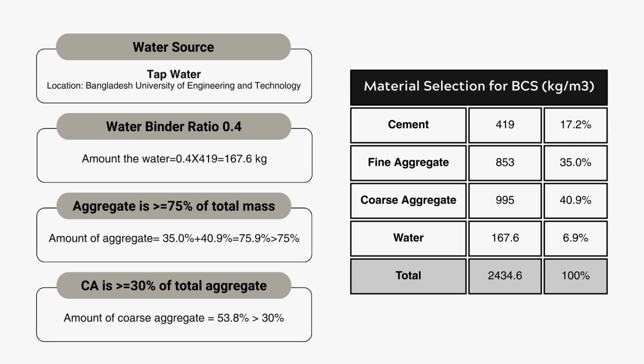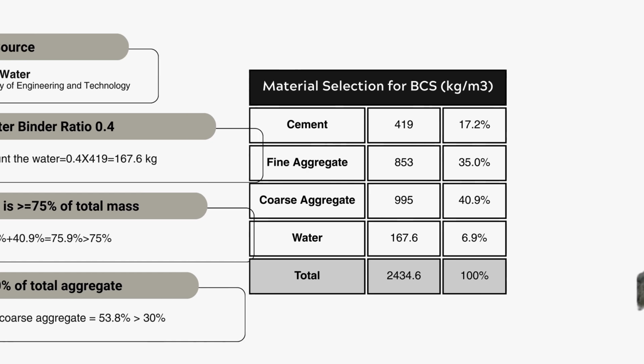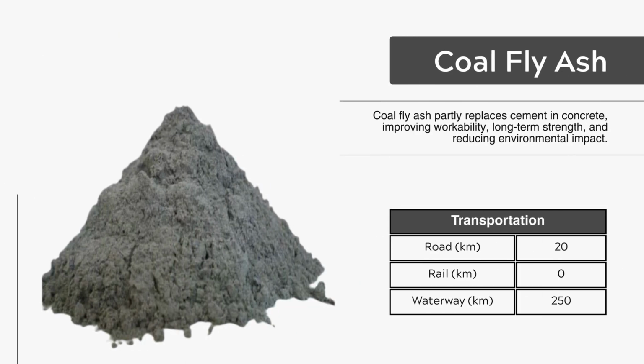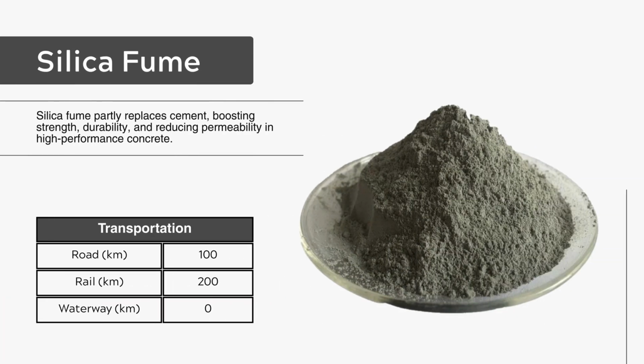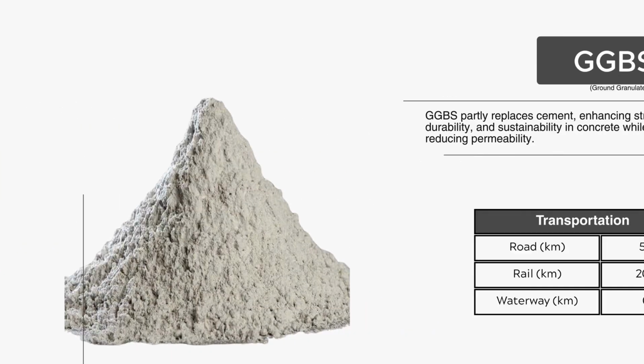In the base case, the mix consists of 419 kg of cement, about 17.2% of the total volume. The aggregate content is the same in both cases, where fine aggregate is 853 kg and coarse aggregate is 995 kg per cubic meter. This careful composition ensures that over 75% of the total mass comes from aggregate, aligning with the ACI sustainability goals. The SCMs, coal fly ash, silica fume, and GGBS are collected from predefined locations, so